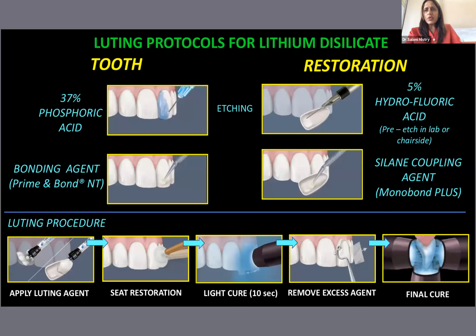Now, very quickly, I want to go through a little bit of the luting protocols, which are extremely essential when you have a lithium disilicate or a silica-based ceramic. On the tooth, it is important that you etch the tooth with 37% phosphoric acid, and then you apply the bonding agent. But on the restoration, which is coming from the lab, it is important that you insist on a 5% hydrofluoric acid pre-etch in the lab, or you also have it at the chair side. It is available in the market. So you etch it with 5 to 10% hydrofluoric acid pre-etch of the restoration, be it a veneer or a lithium disilicate crown. It's very important to etch it.